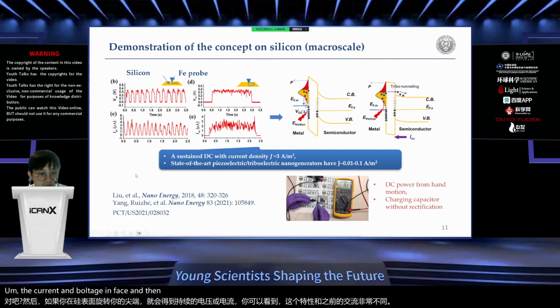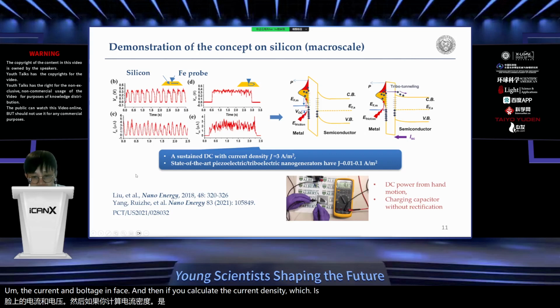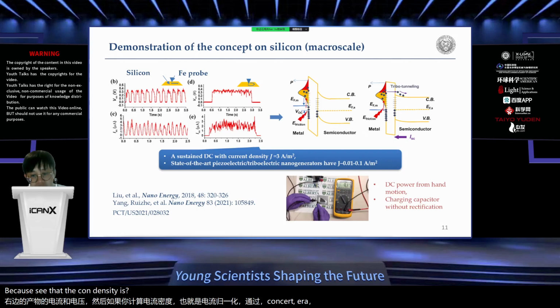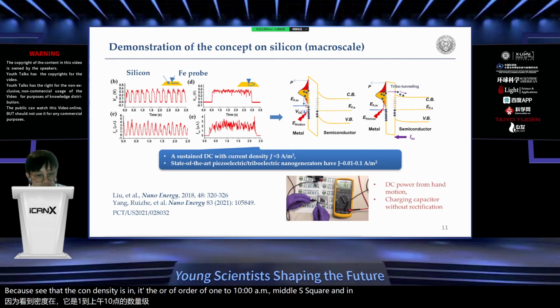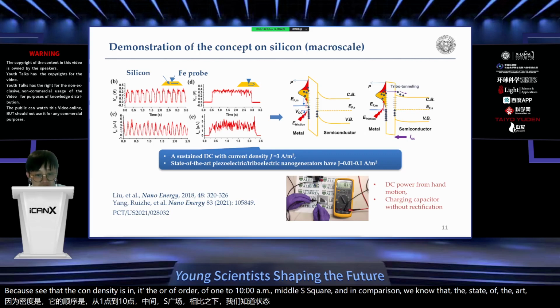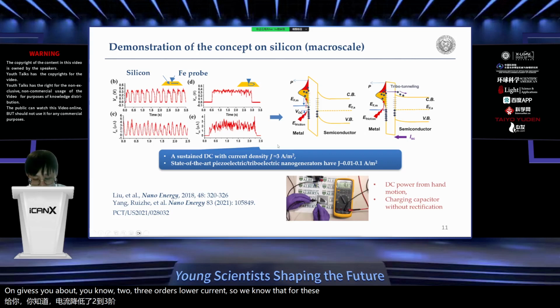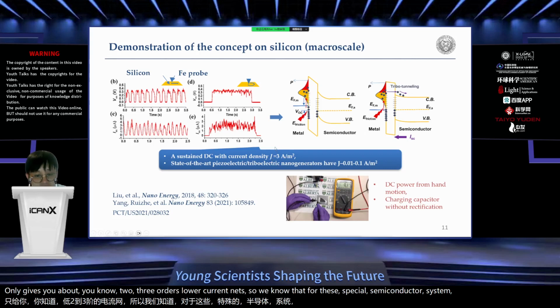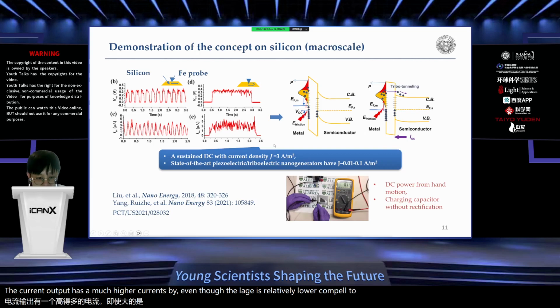And then if you calculate the current density, which is the current normalized by the contact area, you can see that the current density is on the order of 1 to 10 amperes per meter squared. And in comparison, we know that the state-of-the-art piezoelectric or triboelectric generators only give you about 2-3 orders lower current density. So we know that for this special semiconductor system, the current output is much higher, right? Even though the voltage is relatively lower.